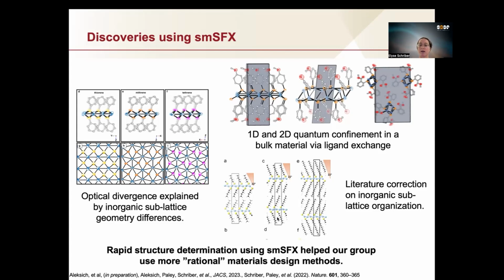We've also been able to correct literature values on inorganic sublattice organization in some silver alkane thiolate 3-dimensional structures. And this is partially because of the challenges in using powder X-ray diffraction, where you have to have a correct a priori model, and it's not always easy to have one of those. So what small molecule SFX has allowed us to do, and what we believe the rest of the community should be able to access, is a way to do rational materials design.